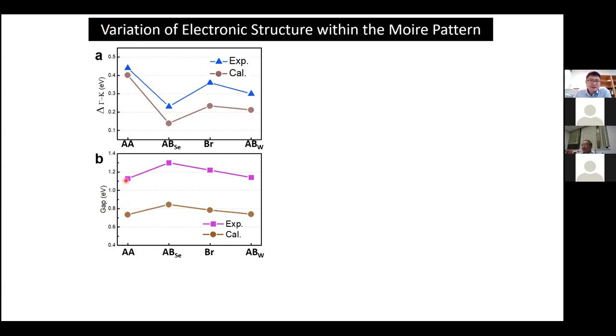And then we also measure the band gap variation. And this is what DFT calculation will show you, that indeed there is a band gap variation. The variation is slightly smaller, but the absolute amplitude is a lot smaller. But this is typical, we all know that DFT has limitations. But to understand why you have such a variation, there is this simple two-level model that I described earlier.